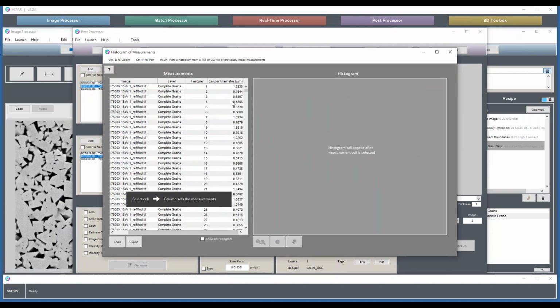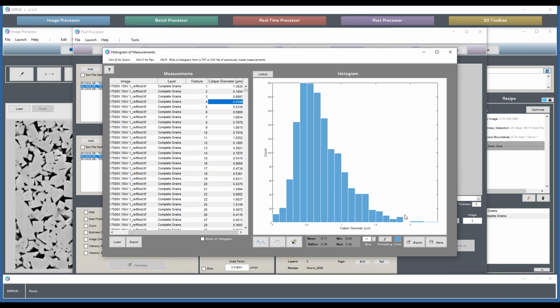And what gave this particular client immense confidence in this method was that they produced nearly identical grain size distributions from their EBSD grains as from the backscatter image grains. So because of this, they were able to adopt this MIPAR solution. What used to take them roughly 10 hours per sample, which meant that they could process roughly 240 samples over 4 months, and that was a fairly standard batch for them.